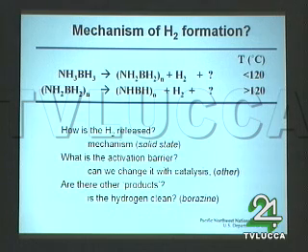It's a solid state reaction. It melts at 114 degrees, and it loses hydrogen quite rigorously at those temperatures. But you can release it from a solid state at temperatures as low as 70 degrees if you're patient, I guess. Or if you put it in a scaffold, things come off a lot faster.